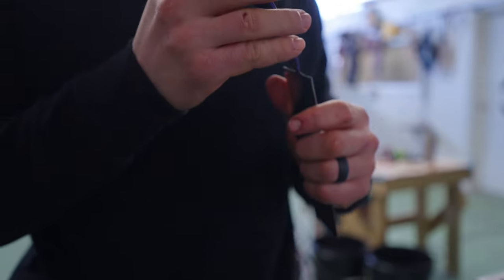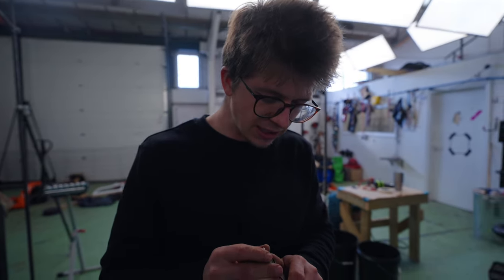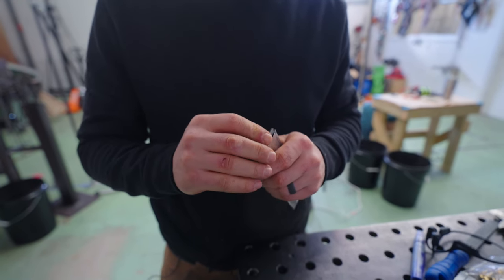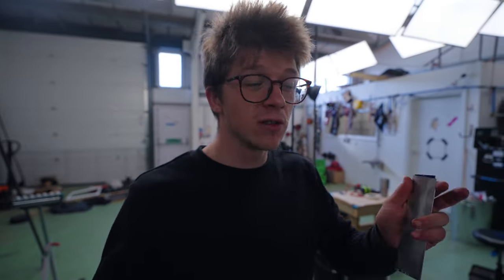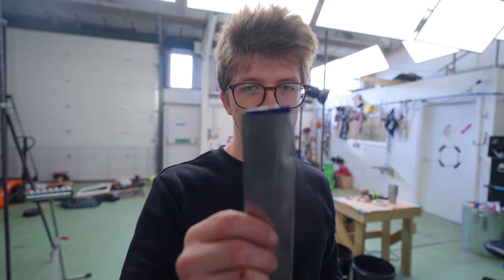So this stainless steel foil bag is hopefully going to be somewhat airtight, keeping oxygen away from the stainless steel blade. Though it is stainless steel, and that would make you think, well, surely it doesn't oxidize. When it's hot, it will. And it'll presumably do something bad, which is why people with a lot more skill, knowledge, experience, and smarts than me have been doing stainless steel quenches with the blade wrapped up.